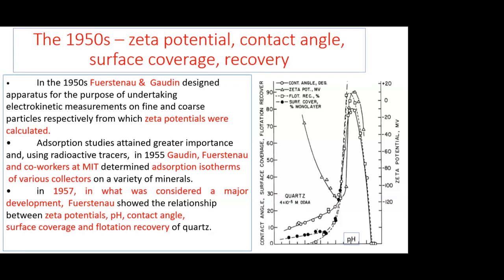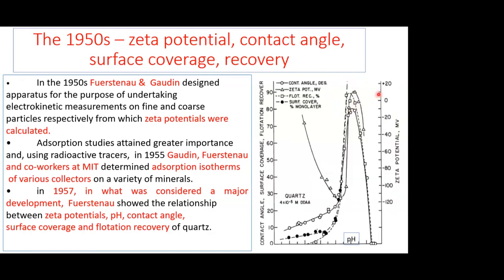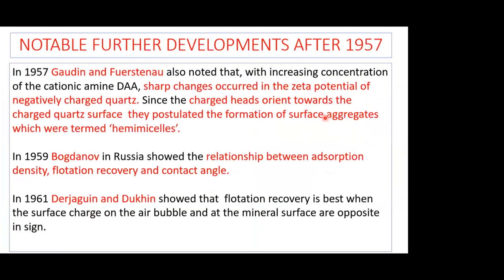And so I've referred now in the third bullet to this figure on the right. Then, of course, they started to try to understand what was happening at the pH that I have indicated. And just let me get my little pointer. So this area here was the focus of attention, the sudden really high rise in surface coverage, and it also coincided with the saturation point of the amine collector. And so they noted, of course, that with increasing concentration there were the sharp changes which I referred to. And since the charged heads orient towards the charged quartz surface, they postulated the formation of surface aggregates, which were termed hemi-micelles.